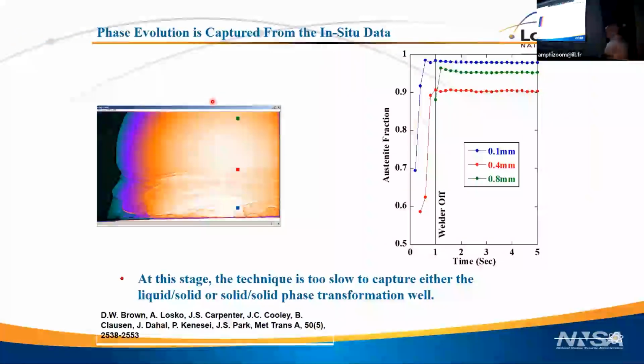So here's what the results look like. This is just an image of what one of these point depositions looks like. And what we did is we deposited these with the beam in 3 different places, 3 different little balls that we made. But we put the beam at 3 different heights so we could get the kinetics of the microstructure formation at these different positions.